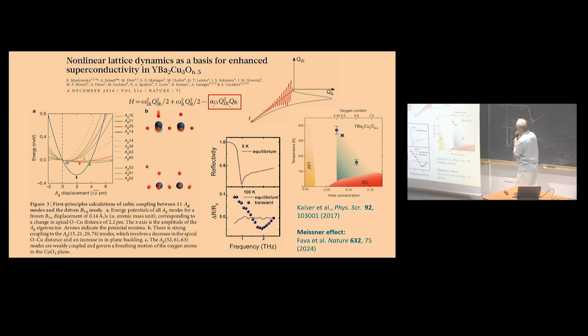And what happens if you have such an effect in conductivity? In reflectivity, you will find finally 100% reflectivity below the band gap. So you can see the effect of superconducting pairing. And this is actually here. You can see such enhanced reflectivity from superconducting pairs. But you can also ask, is it really superconductivity? Isn't it just zero resistivity? So the main evidence is the Meissner effect.